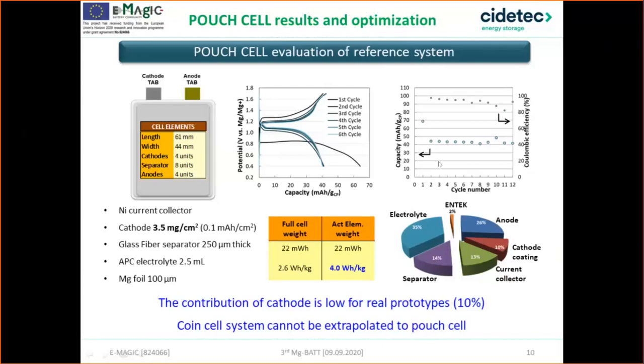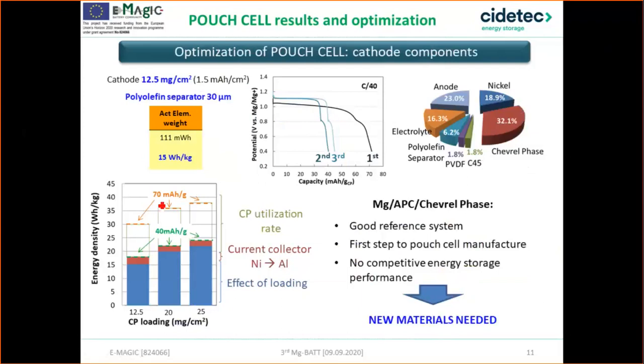Consequently, the following pouch cells integrated cathodes with higher loading, and the separator was replaced by a thinner alternative. This pouch cell was giving around 40-45 milliampere hour per gram and delivered 15 watt-hour per kilogram. This is not a competitive value, but it's a good starting point because the contribution of the key component, which is the cathode, represents a higher percentage of the whole cell.